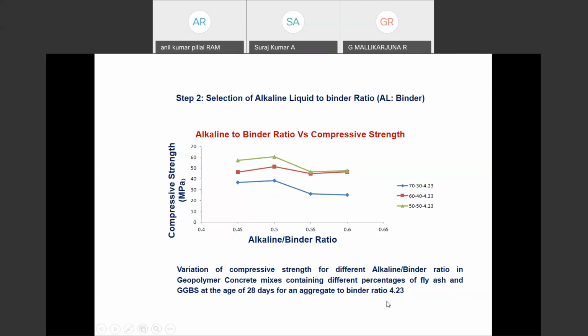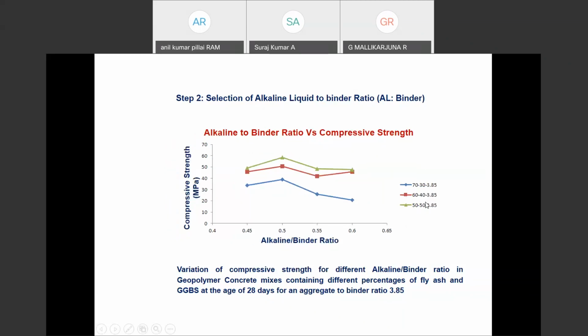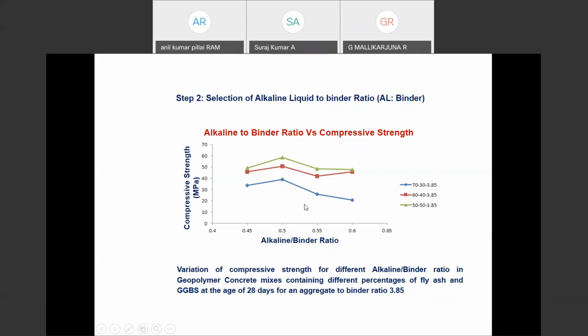And the aggregate to binder ratio, we had reduced to 4.23. And the third one, we had reduced to 3.85. Like that, based on your requirement, your aggregate to binder ratio, you can select based on your strength requirement. You can take any water to binder ratio, that is nothing but the alkaline to binder ratio, for the production of the strength here.